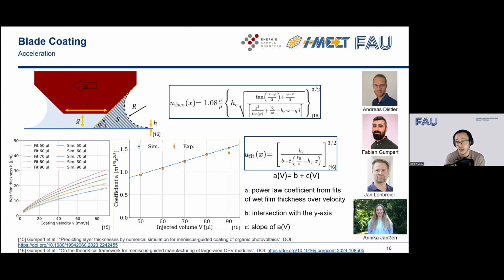Then the intersection of the fit with the y-axis gives you the B parameter, and the C parameter is the slope of the graph that you can see in the bottom middle. And if you put those into your fit formula, you should end up with an acceleration profile that just works to get a homogeneous coating.